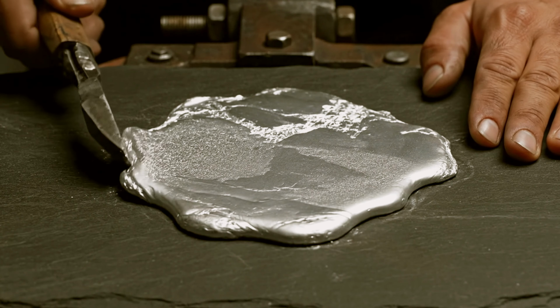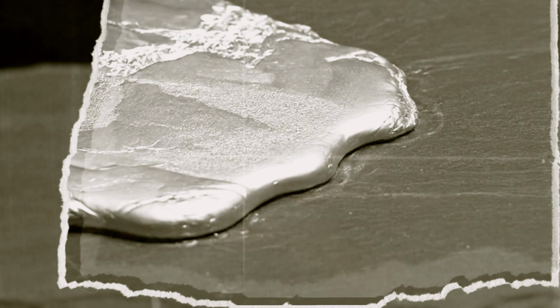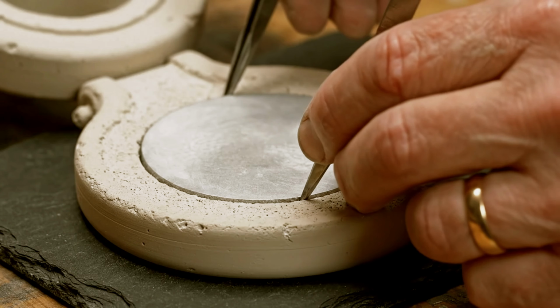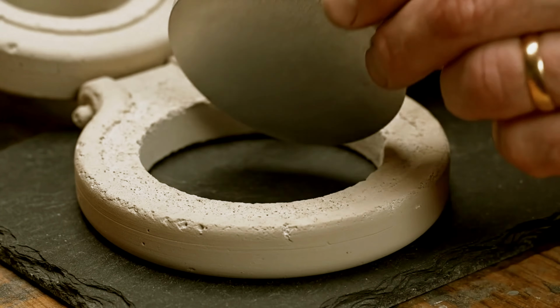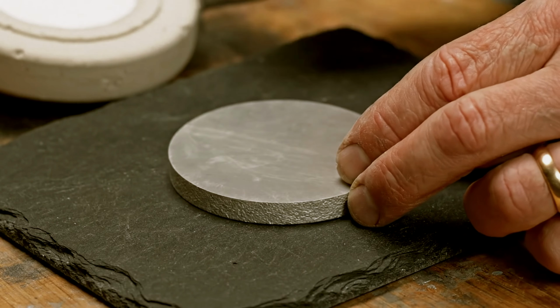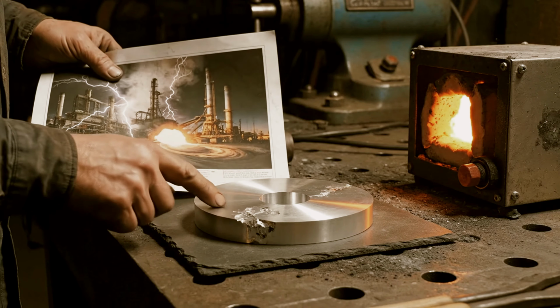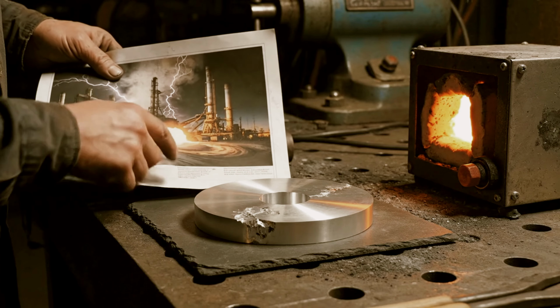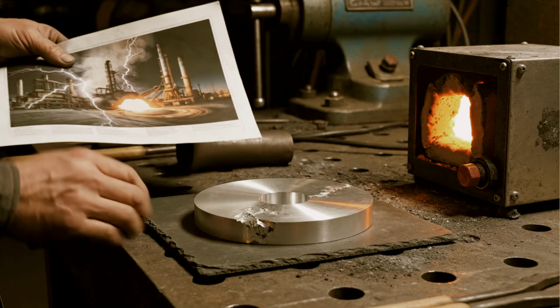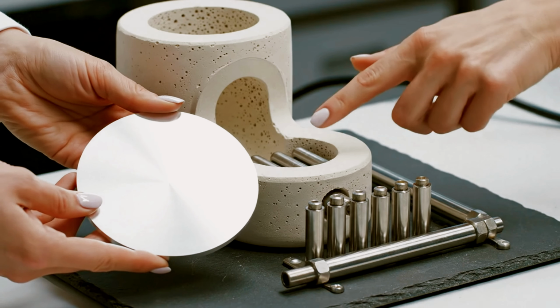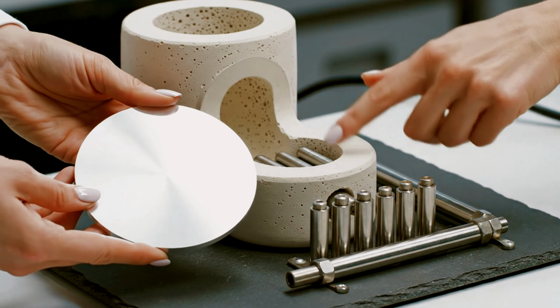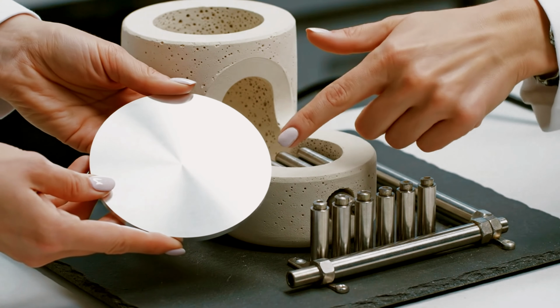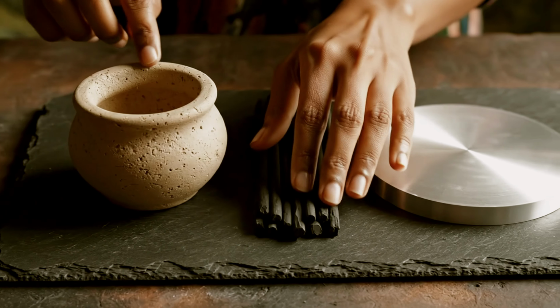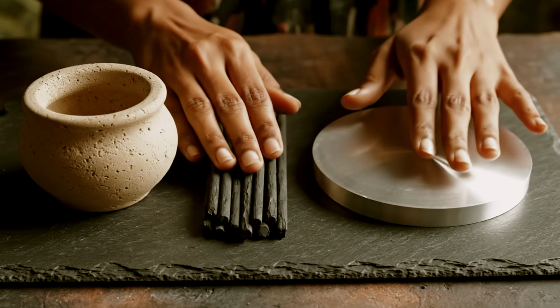The arc dies instantly. Through the opening, the puddle cools visibly. First, it loses its mirror surface. Then a skin forms across the top. Then it solidifies completely into a smooth disc that separates cleanly from the ceramic floor. What just happened at its core is the same process used in the foundries that produce structural steel. The industrial arc furnace is responsible for roughly a third of all steel manufactured globally. What's sitting here on the workbench is a toy by comparison, but the physics are identical.